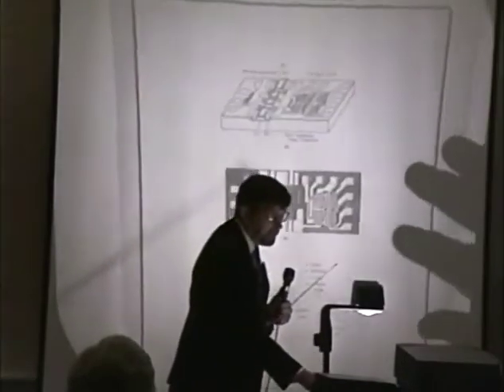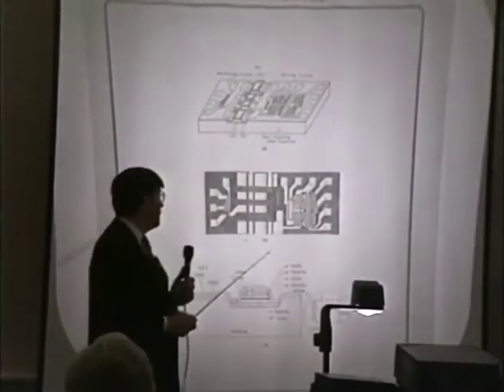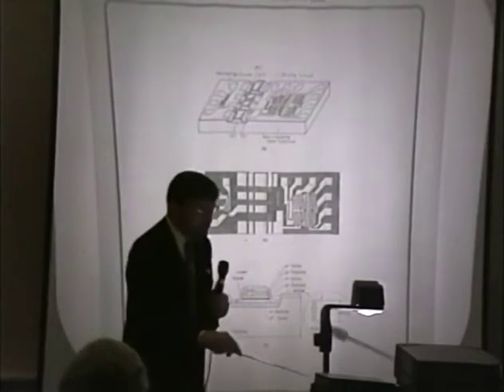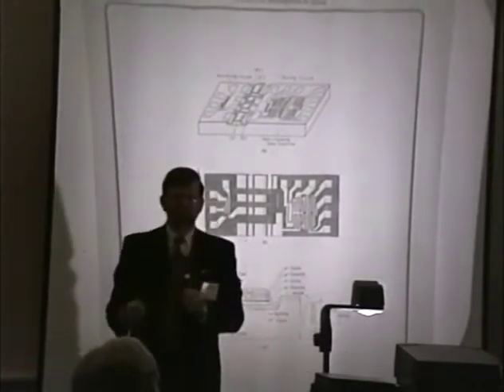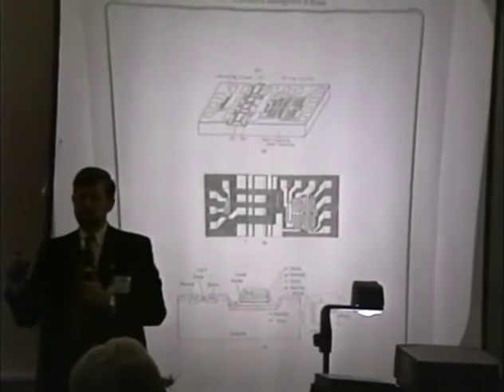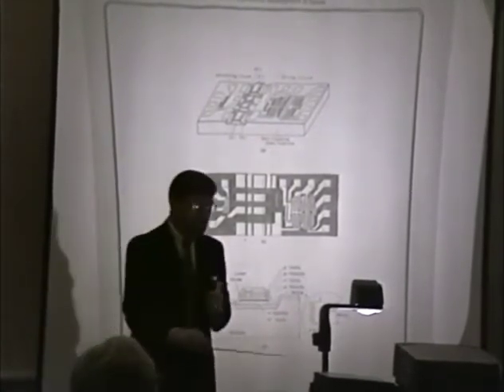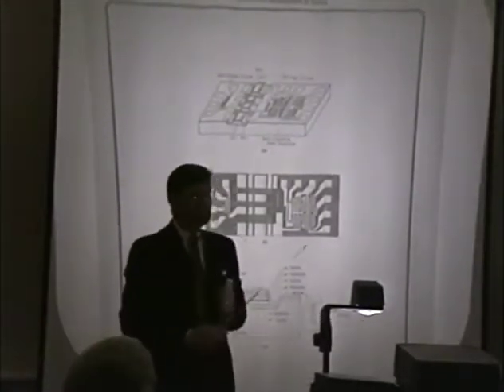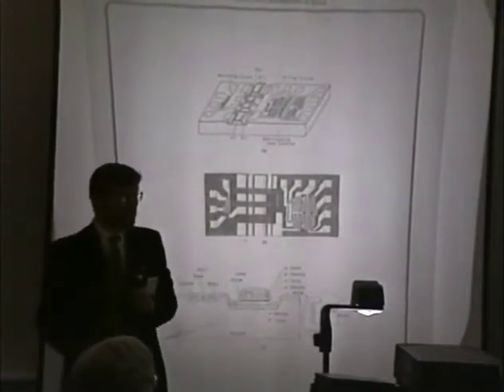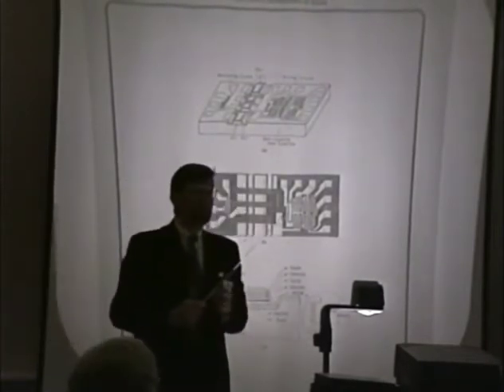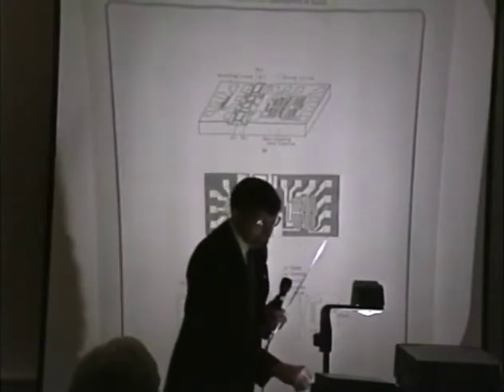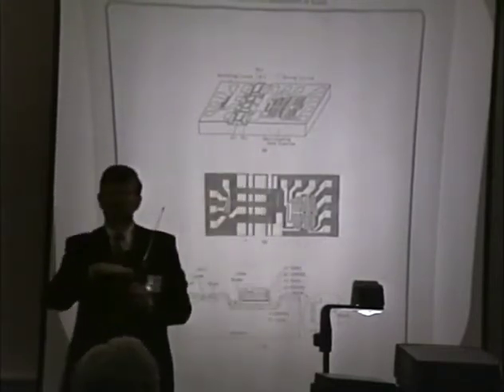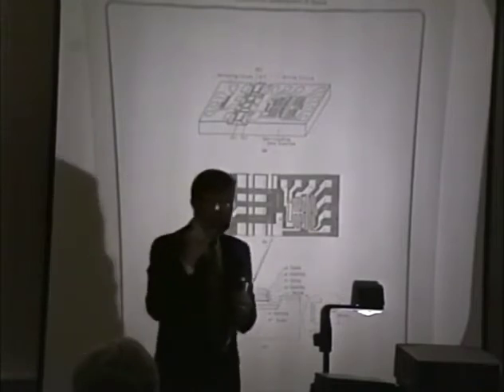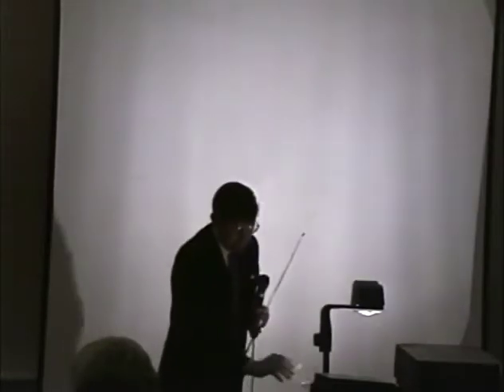Now, that's only a thin film, and you may say, well, why are thin films going to be of any real use? If you look at a microelectronics device, here's a schematic of one, it turns out that the device itself is made only in the top, say, 10 to 50,000 atomic layers of the material itself. And so it's only the top surface of the material that you start with, the silicon wafer is an example, within which the device is made. And as a result, if you make a thin film on top of a poor substrate of very high quality, that is where the device was made in the material in the first place.